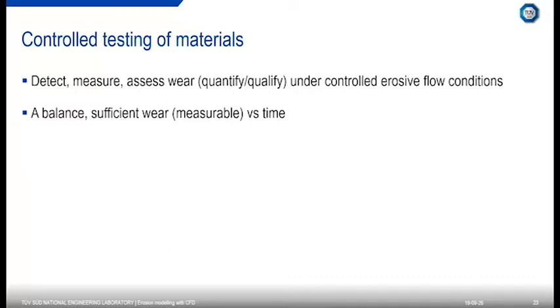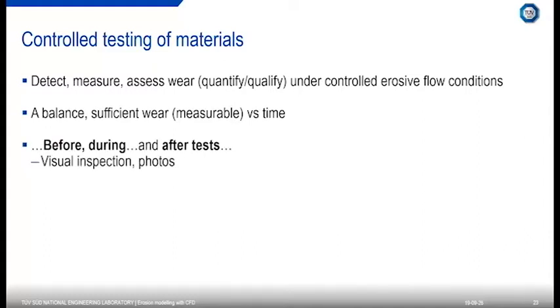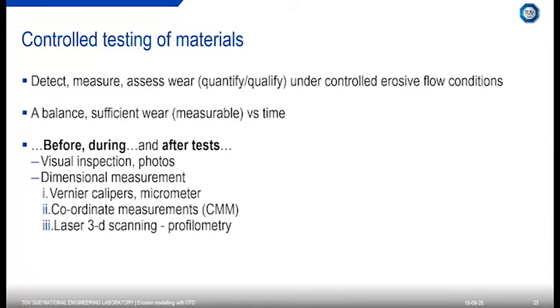Erosion can take years, and that's obviously quite expensive and time consuming to run a test for years. So we will generally accelerate the tests either by increasing the flow rate or increasing the sand concentration to give us something which is measurable. And we've got quite a lot of experience doing that over a number of years. So before, during, and after the test, we'll do a variety of things. We'll take some visual inspections, some photos, some dimensional measurements, some wall thickness measurements, and also weight.